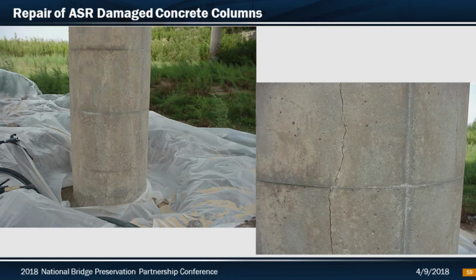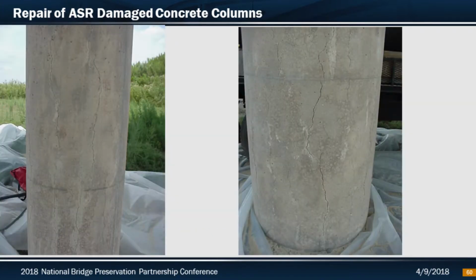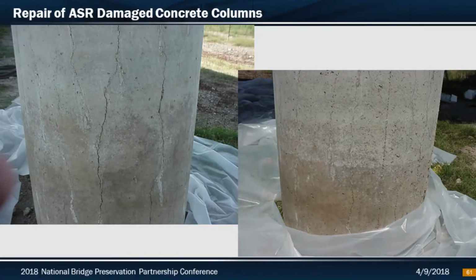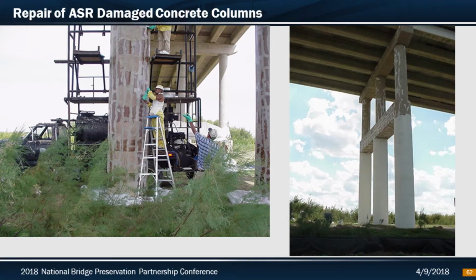Another use of CFRP wrapping. Some ASR damage was noted on another location, Lake Ivy in '04. This was only a 10-year-old bridge structure, and it started to exhibit the typical signs of ASR damage. It was going to be a pretty rough thing to try to repair or replace a bridge that was only 10 years old. You notice the vertically oriented cracks were due to the restraint from the compression and the primary reinforcement. The light transverse reinforcement provided by the spirals was not sufficient to restrain the expanding concrete, resulting in these vertical cracks. So in this particular project, the surfaces were all sandblasted and cleaned.